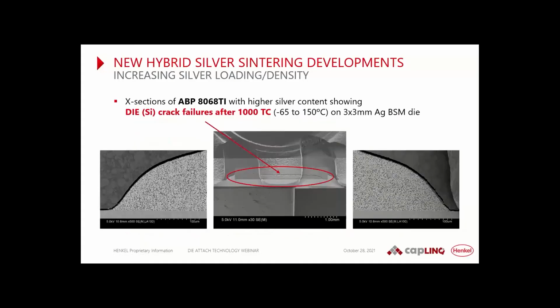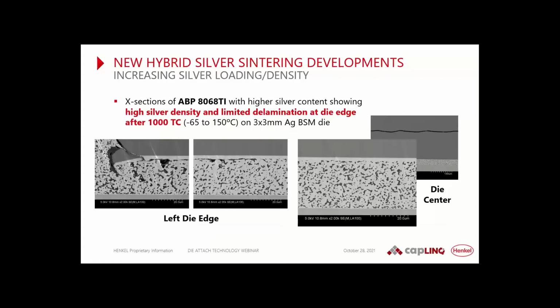And then if we do temperature cycling, we faced a different kind of failure mode in the die. So that is nice as an adhesive supplier saying, hey, we have a great joint, but basically it's of course a failure, and this is something customers cannot accept as well. So for certain applications, this is a very good material, but still this die crack, of course, is something we also need to solve. And here you can see some cross sections, only a small delamination at the edges after 1,000 cycles, within the typical spec of maximum 10%. But indeed, you see here the die crack in the center.